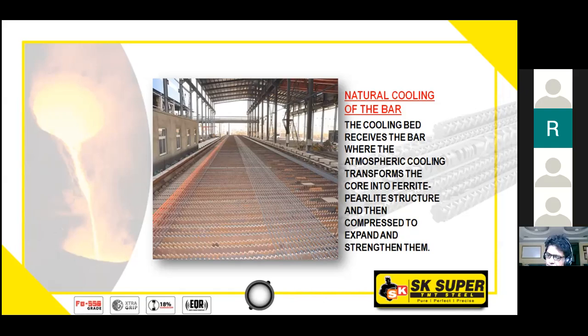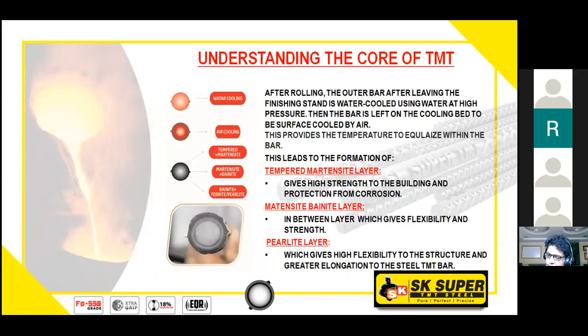Now, what exactly happens to the bar from inside after the quenching and the self-tempering is this. If you cut any bar in the middle, polish the bar and put it in a chemical, you will see these three types of rings in the bar. Every bar which is quenched properly and the temperature is maintained will have these three types of rings.